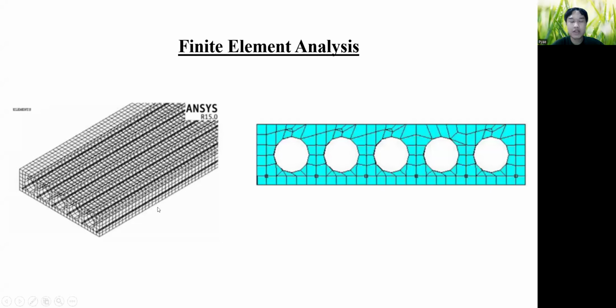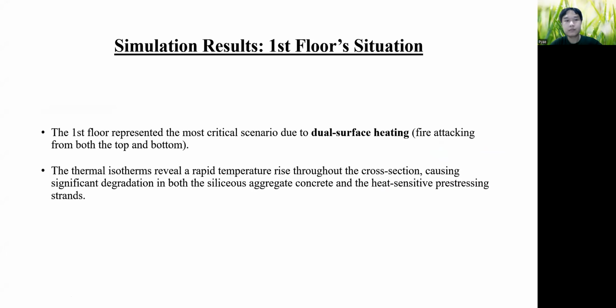This is the representation of the member used in the building. They modeled the member in finite element analysis in ANSYS software, and then they analyzed the building. So the simulation results. For the first floor situation, the first floor represented the most critical scenario due to dual-surface heating. It means the fire is exposed from the top and the bottom as well. The thermal isotherms reveal a rapid temperature rise throughout the cross section, causing significant degradation in both the siliceous aggregate and the heat sensitive prestressing strands.